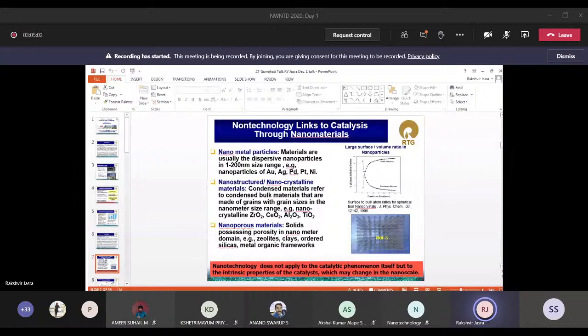We have seen the emergence of zeolites, which are aluminosilicate crystalline materials. They have a pore size less than 10 angstroms. And there are some of the clays, which are two-dimensional porous materials, and some ordered silica. And recently we have seen this very large family of metal organic frameworks. These are all porous materials in which you can do the reactions, and they are of nano dimension, of molecular dimension, and they also influence the selectivity and the activity of the catalyst.